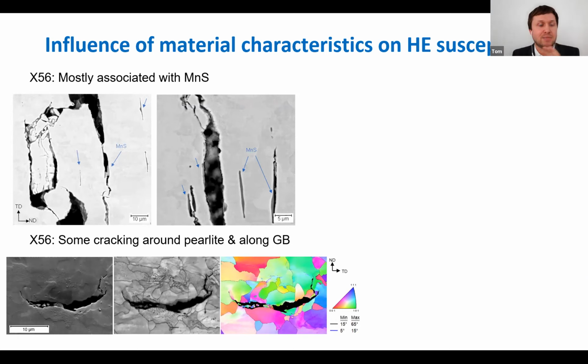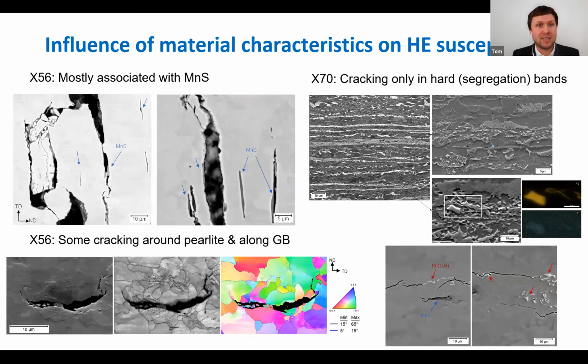And this X56 material was much more prone, much more sensitive to this HIC formation, although the strength level was lower compared to the X70 material. For the X70, we needed to charge much more hydrogen into that material to observe some cracking, again observed at inclusions or niobium-based carbonitrides and the segregation hard bands of the material.